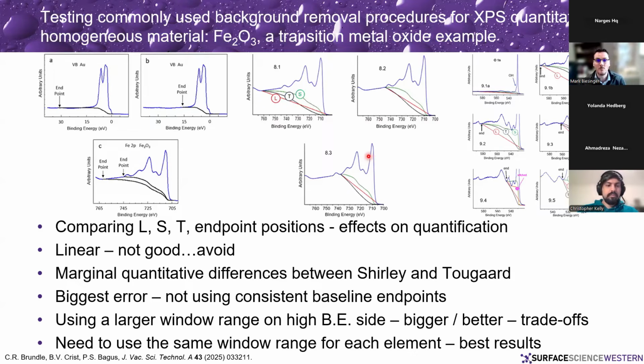And so, particularly for survey type spectra, the biggest error is not using consistent baseline endpoints. So that baseline endpoint between the start and the end. You can see as you change endpoints, no matter what background you use, the area under the curve will change significantly if you have an endpoint here versus an endpoint here. It doesn't matter whether you're using Tougaard, Shirley, or linear. Changes in that background positioning are going to affect things way more.